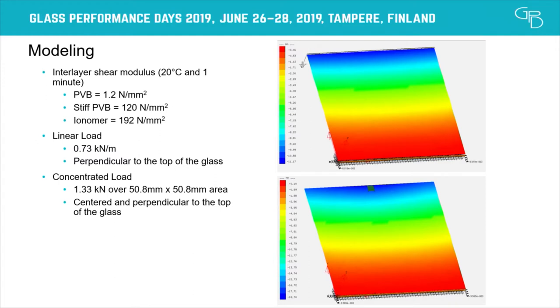Now, this is different than what's in the IBC, because in the ASTM E2353, for this type of system that's cantilevered with no top rail, it recommends a larger load for the concentrated load. The concentrated load was in the center of the glass and at the top, pushing the glass over. Normally I would put it at the edge, but since the laboratory couldn't move the location of the load, they could only do it in the center, I modeled it in the center as well.